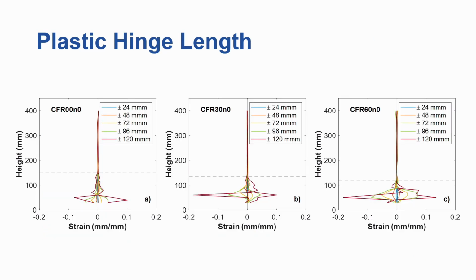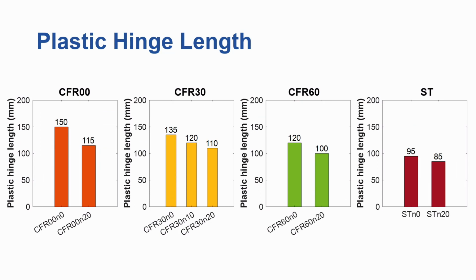So here I'm just plotting some of the results for the concrete filled specimens at 0% axial load. I'm plotting this across the height, and the strains at a given displacement level, and it clearly shows where the inelastic strains develop in the member, and that's basically the plastic hinge length. So this is a summary of the results.